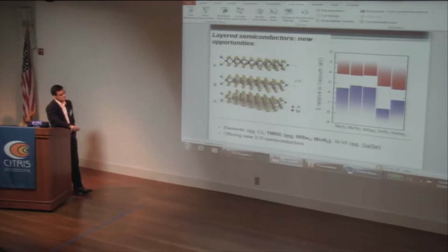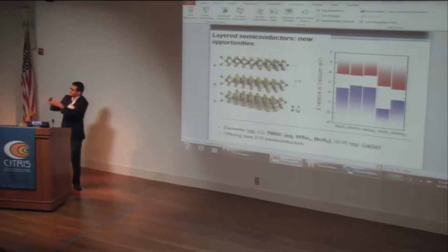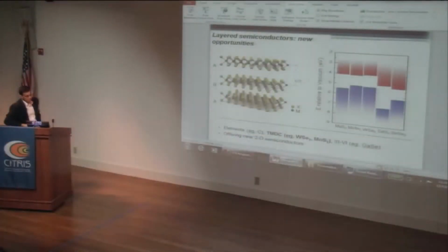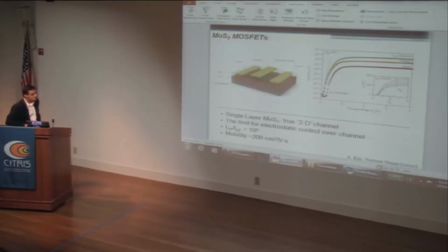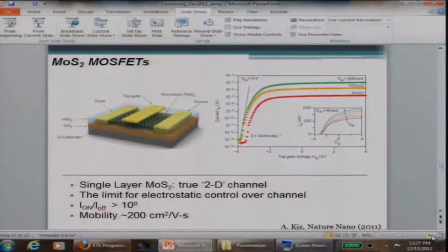There's a whole library of these layered semiconductors. They've been known for decades, especially for lubricants. These layers can slide. They are bonded to each other by van der Waals forces, so they can slide very easily. They're very good lubricants. But they were not really used for transistors until recently. And this was almost 2 years ago, or a year and a half ago, when Andras Kis's group showed that you can make devices out of monolayers of molybdenum disulfide, which is a layered semiconductor with a nice band gap, larger than the silicon band gap.